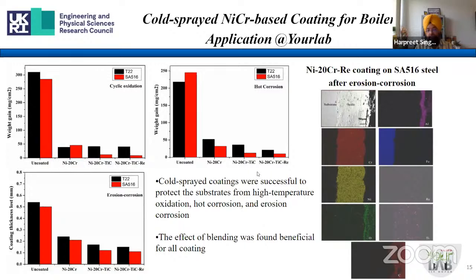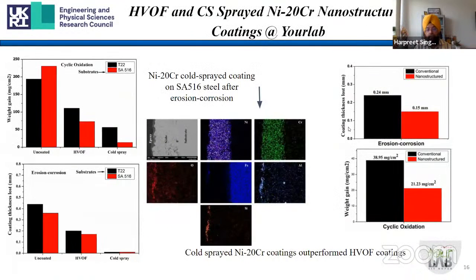So these coatings were very intact. Actually, they reduce our rates in almost all environments, and you can see this coating even after exposure for 1500 hours under cyclic conditions. Nothing happened to this coating much actually. So that was kind of interesting and encouraging for us. Of course, we continue that work.